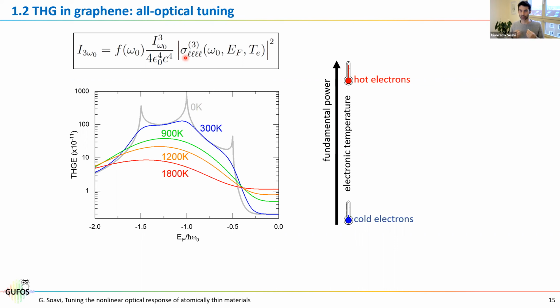However, what is the idea? So what shall we do in order to achieve all optical modulation? We said that the intensity strongly depends on the electronic temperature. But on the other hand, the electronic temperature is an indication of how much energy we transfer from the optical pulse to the material. So if we now increase the power that we shine on our material, we will also change the electronic temperature. And this is an indication that we can use light to modulate the third harmonic efficiency.